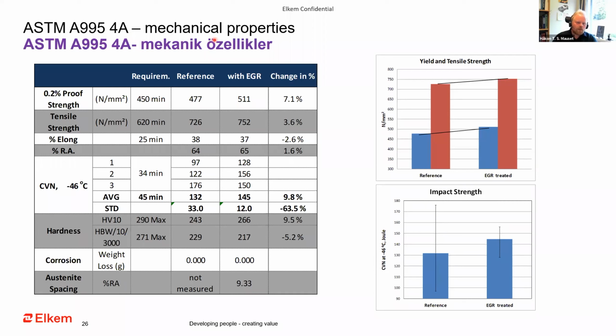We will not dive too much into all of these numbers, but we typically see that for the yield strength, the reference was 477 megapascals. They achieved 511 megapascals. So that's a 7.1% change. For tensile, we see the same, it went up from 726 to 752. That's a 3.6% change. And then perhaps the most important is the Charpy values.